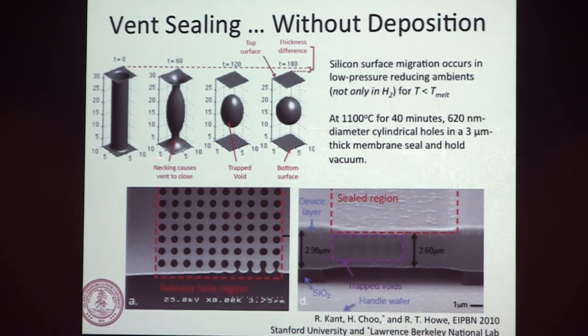And Rishi, being a part computer scientist, wrote the code, which was no mean feat because of these bifurcations, to predict if you had a cylindrical hole, when you annealed it at 1100 degrees for 40 minutes, what would you get? He predicted void and he predicted volume contraction because of mass conservation. And lo and behold, you see the volume contraction. You can see the ghost-like appearance of those voids in there. So in any case, to apply this to MEMS packaging, we don't have deposition anymore. Okay, we just heat it up and you seal your membrane. We could do it in hydrogen. We can also do it in any low-pressure reducing environment, including ultra-high vacuum.